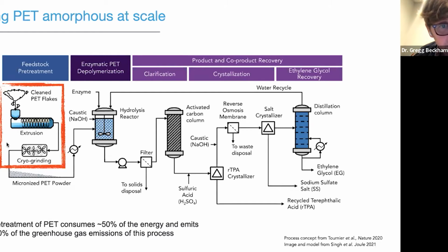And this feedstock pretreatment enables the reduction of crystallinity from around 30 to 40% down below 10%. And then the rest of the process is essentially the enzymatic hydrolysis step, and then this goes through a downstream processing step to recover ethylene glycol, a sodium sulfate salt, and then recycled terephthalic acid. So your two primary building blocks, EG and TPA, of your PET.